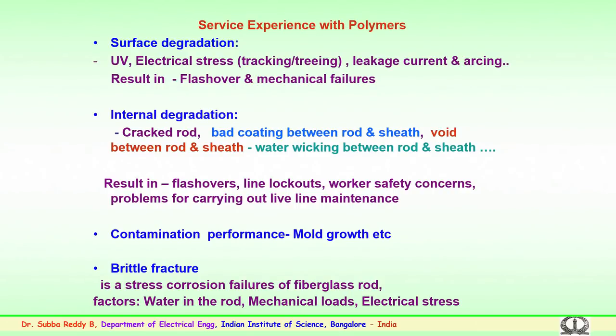Arcing could be surface arcing, what we call scintillations or partial arcs. This could be due to the formation of dry bands and wet bands on the surface, because the surface may not be continuously wet. These small bands, formed due to rain or fog conditions, make the surface partially wet and partially dry, resulting in the arcing known as partial arcs or scintillations. This depends upon the surface conditions and the surface resistance offered. So, dry band and wet band formation followed by leakage current could lead to flashover, and sometimes mechanical failure also because of fiberglass rod failures, where the line could get detached.